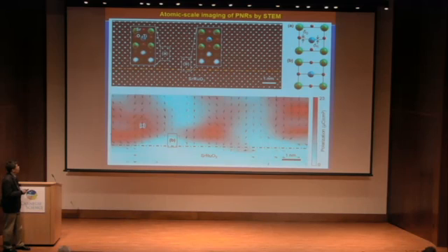So for the titanium ions, you see the oxygen displacement and map it out. In these regions, these red regions show pointing-down polarization, and that shows some existence of nanopolar regions, not all connected, but you see these features.